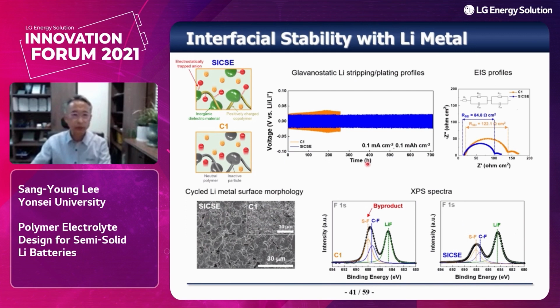We have measured the interfacial stability with Li metal, and stable plating and stripping behavior was observed, and EIS profiles verified this. We also measured the surface change on the cycled lithium metal using SEM and XPS spectra. The side reactions were suppressed by incorporating the single ion conducting polymer. So the single ion conductor with a high cation transference number played a vital role in enabling stable lithium stripping and plating on the lithium metal surface.